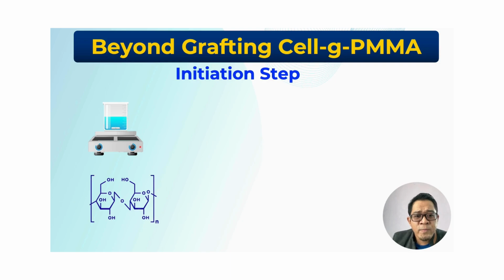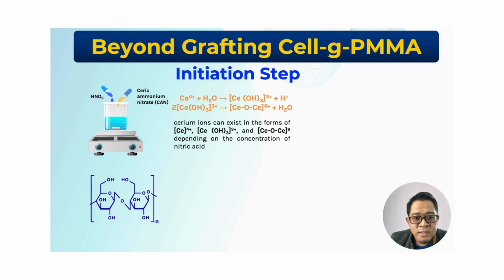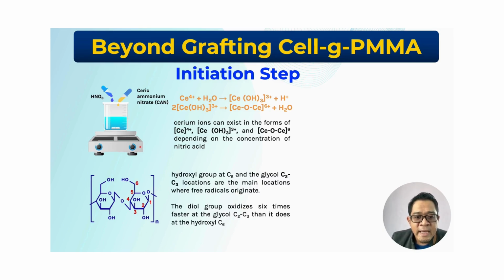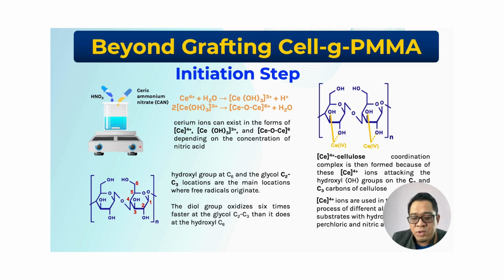Next, we go through the beyond grafting of cellulose grafted PMMA. In the initiation step, the cerium ion can exist in the form of Ce4+, Ce3+, and Ce6+, depending on the concentration of nitric acid. The hydroxyl group at C6 and the glycol C2, C3 location are the main locations where free radicals originate. The diol group oxidizes 6 times faster at glycol C2 to C3 than at the hydroxyl C6. So, the reaction will occur at C2 or C3.